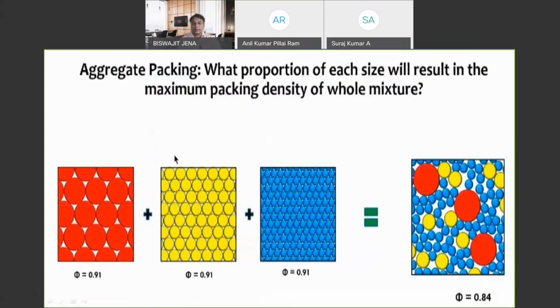Now aggregate packing. How do you do aggregate packing? If I have one size of aggregate, the best I can do with a small size aggregate is to get a packing fraction of 0.91. But if I start adding more and more, you have a separation effect, spacing differences and so on, and your packing fraction will start to come down. Again, this is not applicable to all sizes. This is applicable to really small sizes, on the micron scale. If you look at hexagonal close packing, you get 0.74, which is the theoretical maximum packing, and this can also be manipulated by adding a few more sizes to get to a higher value.